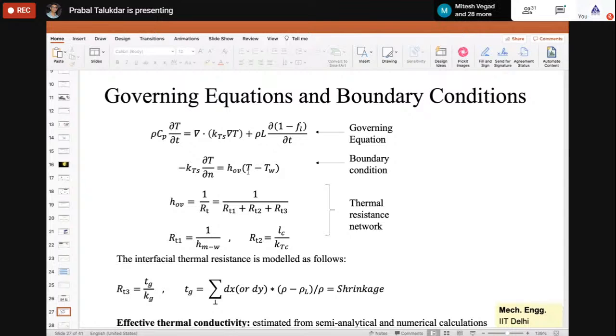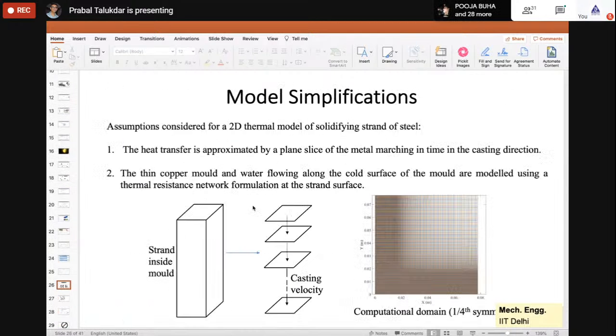The other important thing in this problem is the boundary condition, because in this case we don't have any heat flux information. As I told you, we don't work with the heat flux information. Instead, outside we have cooling water, then we have a thickness of the mold, and then there is an air gap. There are three resistances here in terms of a boundary, right? If you think about a resistance network problem, outside the solidified strand you have one air gap. After that, you have a mold which has a certain thickness, and outside you have a cooling water channel. So there are three things which give you certain resistances.